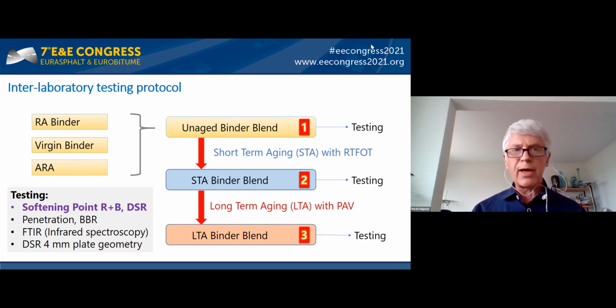But still, if you divide it by 17, you only get about 300 grams of this binder, which you have to test and age. So you test it out in the 3 stages. So we don't have a lot of material for testing. So we need some test methods which don't use a lot of material. And these are mainly softening point, ring and ball, penetration, and DSR measurements.